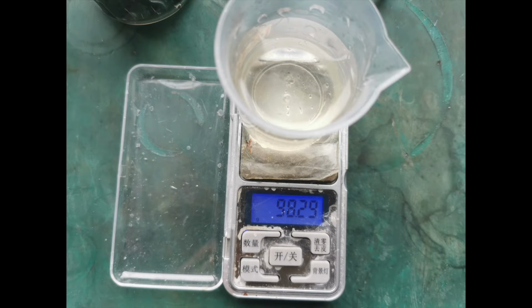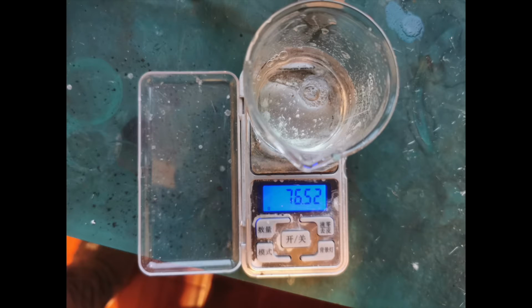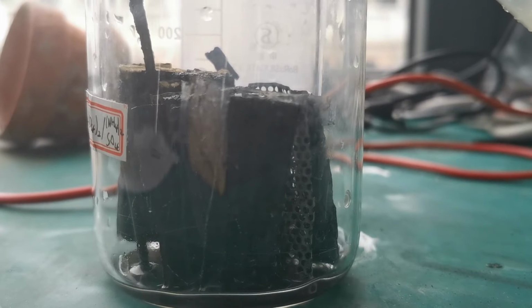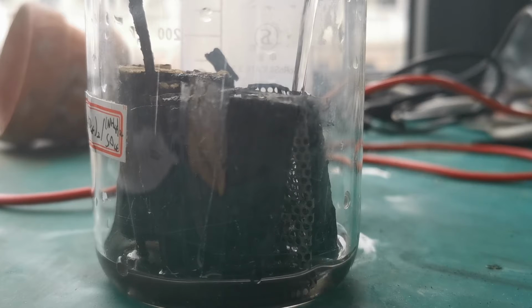Then I weigh out 100 grams of 37% sulfuric acid, which will leach the nickel compounds into solution. Note that this is a rather large excess, and 75 grams of acid would work as well. The sulfuric acid is then poured into the beaker with the battery material.